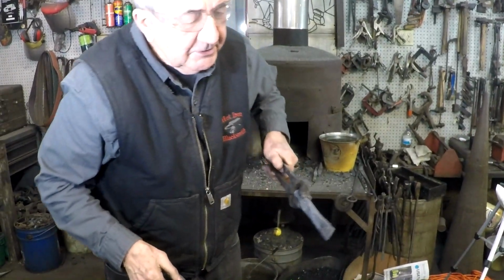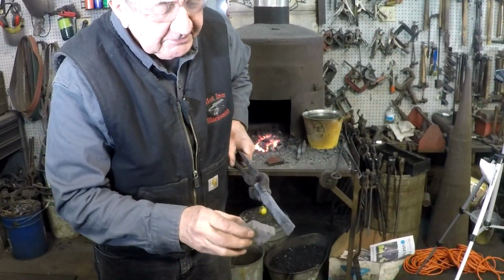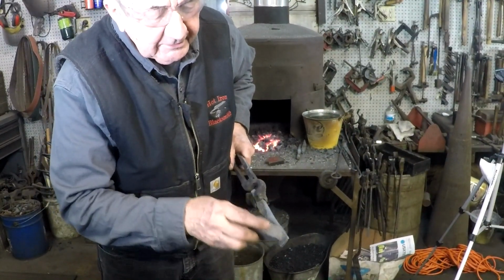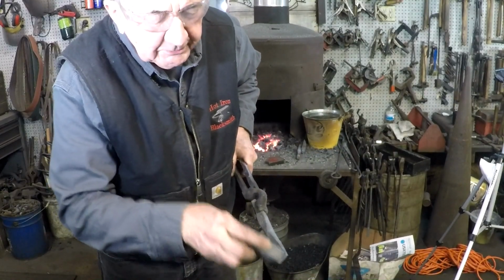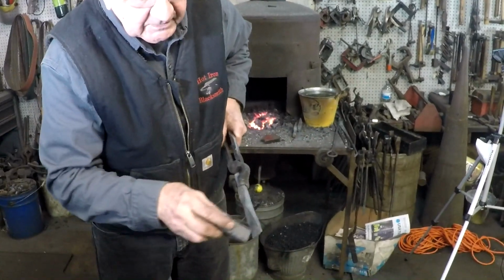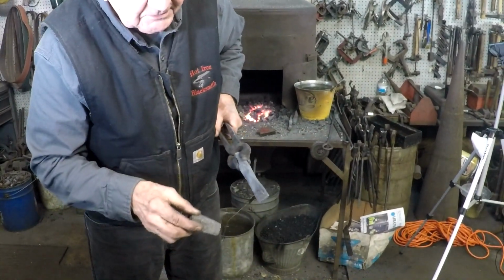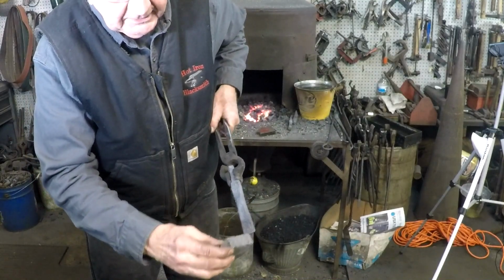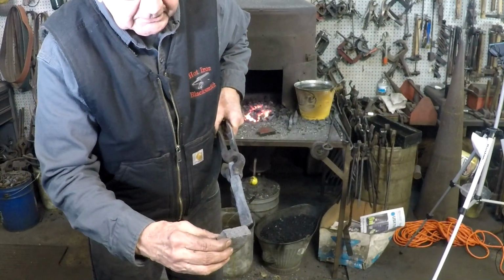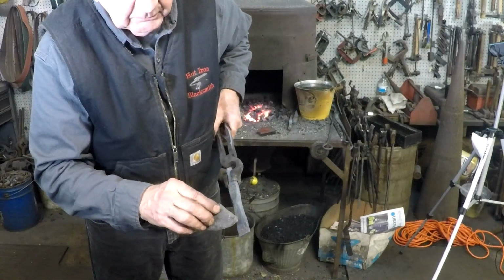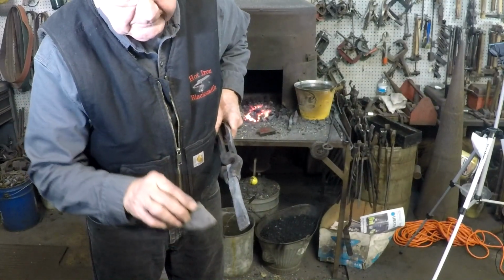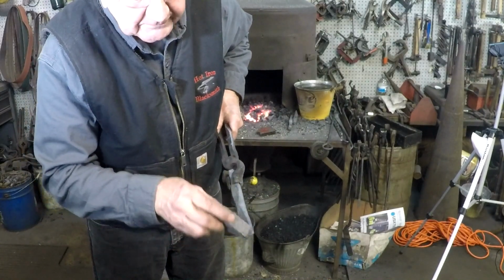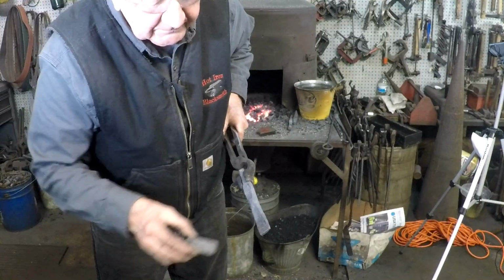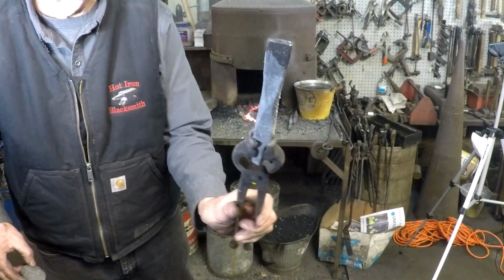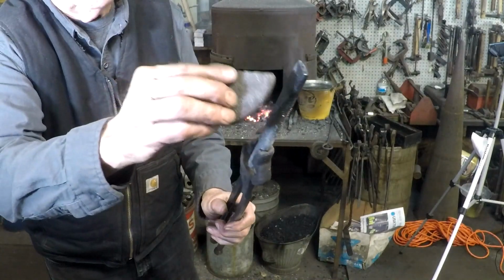Okay, so if you can see in the light, the colors are blue back here, and they are slowly turning to a brown color out on the very tip of the punch. When it gets to a straw color brown on the tip out here, I'm going to go back in the water bucket and cool it off up to about where it's gray in this area. So now I'm at that brown color. It may be difficult for you to see, but believe me, it's brown. So we're back to the wet condition, and I did not dunk it in the water any more than I had to, up to about 1.5 inches.